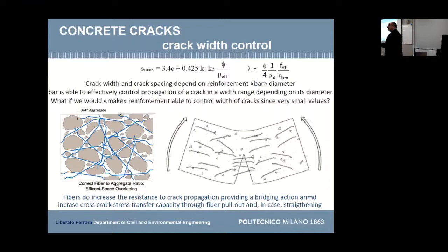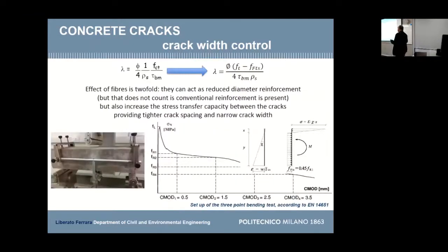Just go into fibers. Fibers can have millimeter wire diameter. Except for special mixes and special cases, they do not increase the tensile strength of concrete. It's not that. But they increase the capacity of the concrete to resist crack propagation. So they control the opening of the crack. And all of us working with self-healing technology, this is important for durability, but we also know that a crack which is narrower, has a narrow volume, is more easy to be filled, to be repaired.